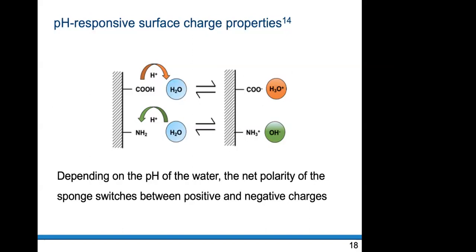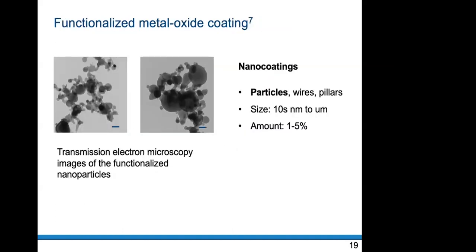However, they do not have the ideal surface energy, which is thermodynamically freely available energy, with which the bacteria can also attach to surfaces via van der Waals and hydrophobic forces. So for that reason, what we can do is use these nano coatings. These nano coatings can be functionalized with different groups, like alkyl chains or amine groups. And we can also use them in different shapes, like particles or wires or pillars, where the spiky structures tend to break the cell membrane much more easily compared to the other structures. They can be in any size, from tens of nanometers up to a micron. And as I said before, we can use this material as a coating, so an amount of about 1 to 5% should be enough to achieve the required properties.